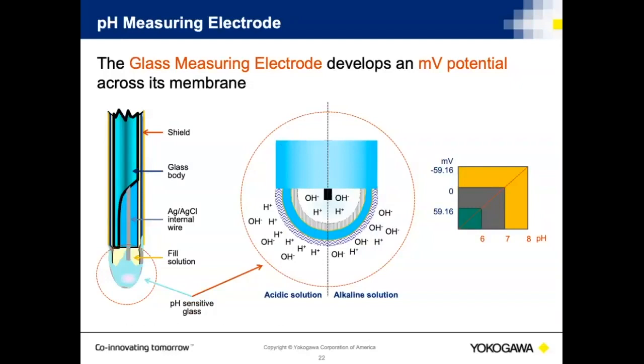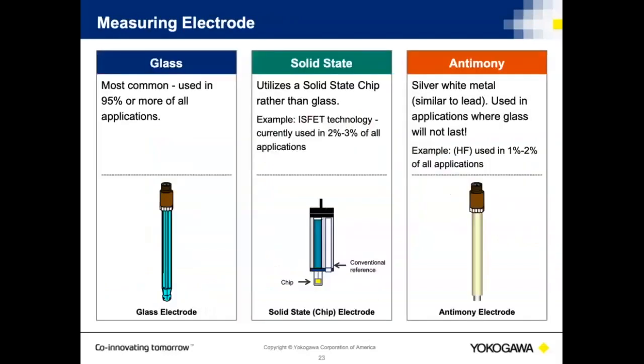That membrane then puts out 59 millivolts per pH unit, depending again on the temperature. So more hydrogen ions, the higher the output of the electrode, positive. If I go the opposite direction, if I lose hydrogen ions, then I lose them at a rate of 59 millivolts per pH unit. If you look further into this measurement, we can use glass for making an electrode, we can use a solid state chip for making a measuring electrode, or we use antimony electrodes. The most common is the glass electrode.